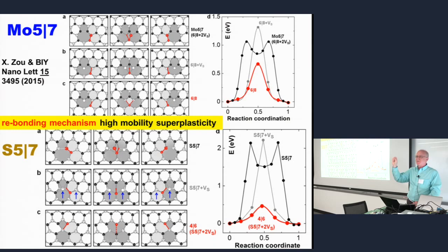By adding sulfur or removing sulfur, you can reduce the barrier. Normally, this is a brittle material, which means that they should not move at all. They're sessile dislocations. But at some composition, your barrier is reduced to almost nothing. This is a very low barrier. And if you have a dislocation with this low barrier, it should glide very easily.